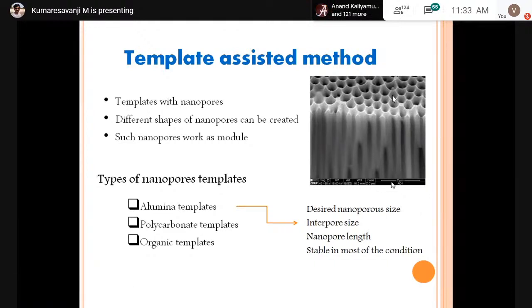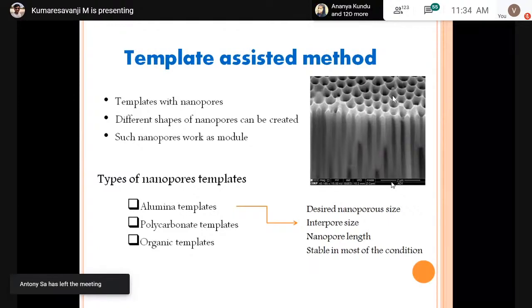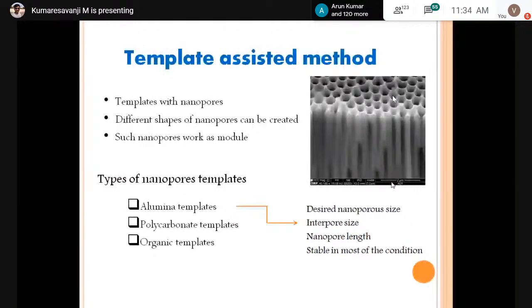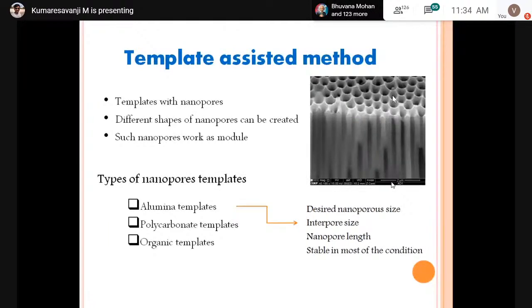So the alumina template can withstand up to 850 degrees Celsius. After that, it crystallizes. But also the alumina template, that aluminum oxide I'm talking about, is stable for most of the chemicals. So while we are preparing this alumina template, we can tune the nanopore size. We can get the nanopore size depending upon our requirements, and also we can change the interpore size. We can change the nanopore length, and also it is stable in most of the conditions.